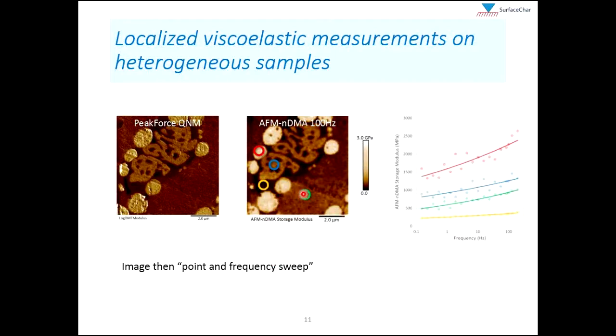This is the storage modulus image. And then you can actually point and frequency sweep. So point and shoot into different areas, into the different components, which is what we've done here, and collect a full frequency sweep of the viscoelastic moduli. So here we're showing the storage modulus as a function of frequency up to 200 hertz. We did not have the high frequency external actuator loaded here for this sample. And so now we can see the storage modulus as a function of frequency for these 4 components.